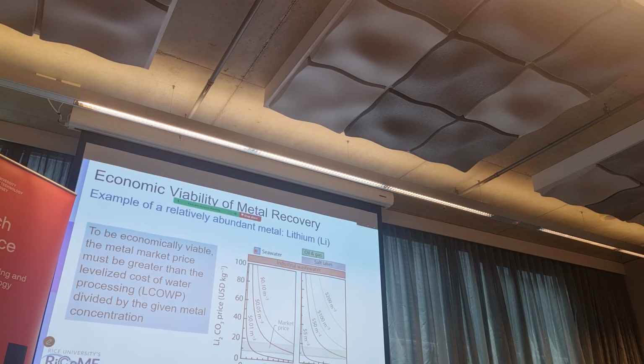Now we look at seawater—this is the concentration of lithium in seawater. You go down to this curve and see where these lines intersect with the current price. So I tell you, in seawater, to be economically viable—even with a process that is 100% selective—you need to process the water at about less than 1 cent per cubic meter, just to process and pump it through your separation process.